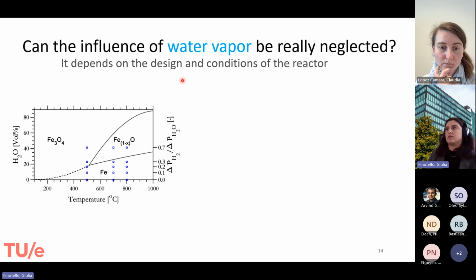What it is really depends on the design and the condition of your reactor. If we look at the thermodynamic plot, we can really see that, especially for lower temperature, because we are talking about equilibrium reaction. If we are doing reduction at a lower temperature and we increase the water vapor content, we end up shifting the reaction towards the magnetite and not towards the iron. So we shift the reaction toward the hydrogen and magnetite production.